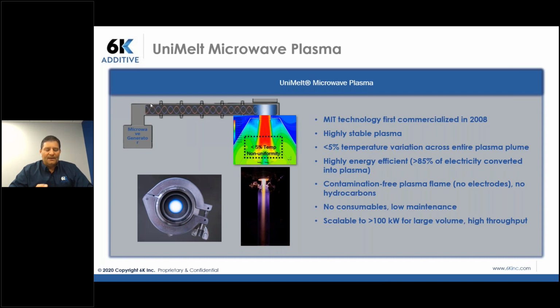So a few things that affords us. It's highly stable. It has a great temperature uniformity throughout the plasma itself, from the core outward, and it also is highly energy efficient. So the energy that you put into the plasma system, the microwave couples, and the energy from the microwave is about 85% efficient to the plasma. What all that does is it gives us a really nice processing zone for a wide variety of materials. So we have a pretty broad-based product offering, and it's facilitated by the fact that this microwave plasma is so controllable and that we can create a nice material processing zone within the system itself.